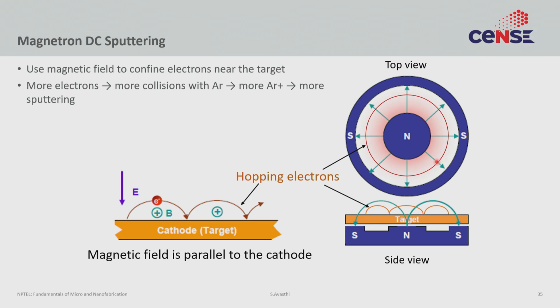You can force the argon plus atoms or electrons, the electrons can be forced to stay closer to one of the electrodes. So, locally the concentration of electrons can be enhanced at the expense of a lower concentration of electrons somewhere else. So, instead of a uniform plasma, now you have a biased plasma where electrons are all tightly confined close to the one electrode. And that electrode tends to be the target. So, by forcing the electrons to be very close to the target, you have now artificially enhanced the concentration of electrons without actually changing the pressure, right?